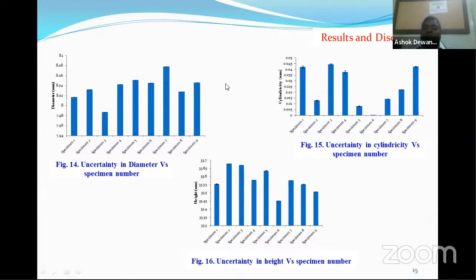Clear? So similarly, our cylindricity, ideally it should have been 0.04, but you will see its value is something different, not everywhere the same. Ideally all specimens should have the same value, but you will see there is variation. It means your process is not as consistent as it has been claiming.